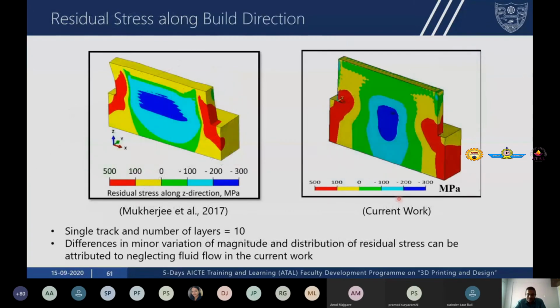You can see that these are our predictions for residual stress along the build direction, and these are the predictions from the model published in literature, and you can see that the predictions are in reasonably good agreement, okay. The minor differences in the magnitude and distribution of residual stress can be attributed to the fact that we have neglected fluid flow in our models, whereas the authors have considered fluid flow. Now, neglecting fluid flow can result in over prediction of temperatures and over prediction of cooling rates, and that could be the reason why our results were slightly different from the ones published in literature. So these are the residual stresses along the build direction.